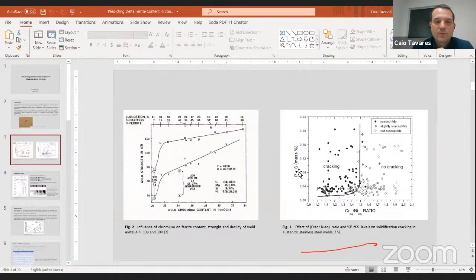Yeah, the mechanism is that we have, in the chemical composition, traces of those elements, phosphorus and sulfur. During the solidification, they go to the grain boundaries, and you lose resistance of this component, because you have those trace elements on the grain boundaries. That is the point that can generate cracking in castings or weldings. So in the case of weldings, physically that is what happens: you have those trace elements, that trash, on the grain boundaries, and you get embrittlement in these areas.